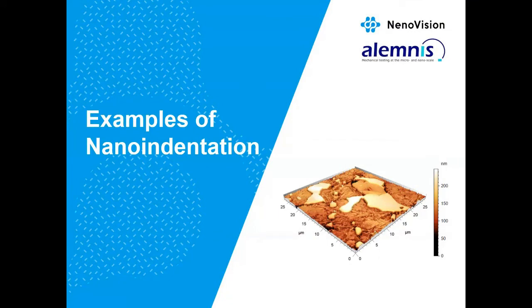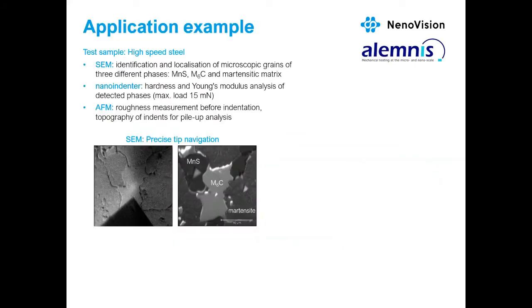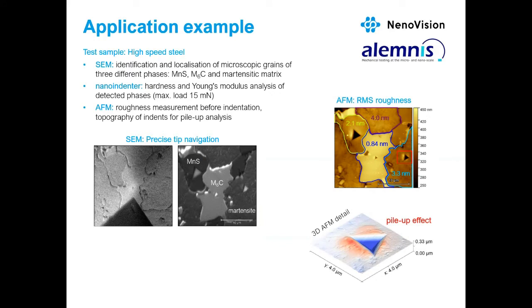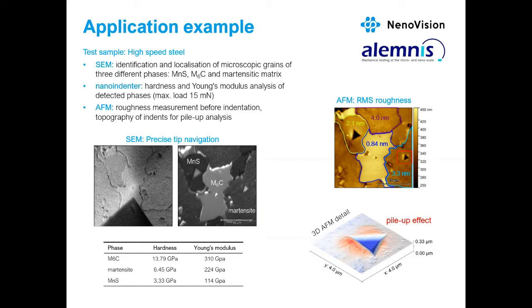So let's have a look at a few examples of using this 3-in-1 solution. Here we investigated high-speed steel composed of 3 phases. As we can see, we found these 3 phases and did indents. Here is one of the indents, and we can see very nicely these phases in SEM contrast of backscattered electrons. Then, after the indentation of several areas, we measured the topography, so we can determine the depth, the pile-up effect, etc. And then we can calculate from the curves the hardness, Young modulus, or other mechanical properties.